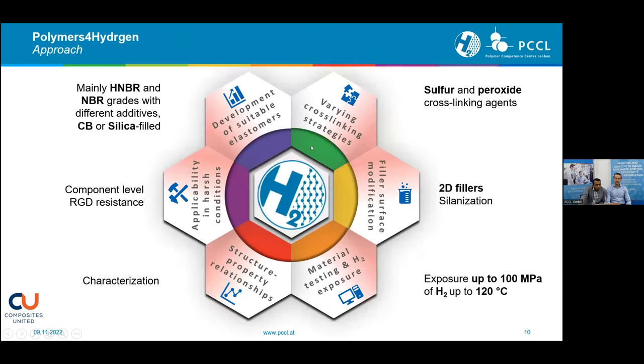So what is our approach to address these challenges? So here we see from polymers for hydrogen, we have different aspects. Here, for example, we have developed some suitable elastomers. In this case, I show you some HNBR and NBR grades with CB and silica filler. And we consider here also varying the cross-linking strategies, for example, sulfur and peroxide cross-linking for these rubber grades.